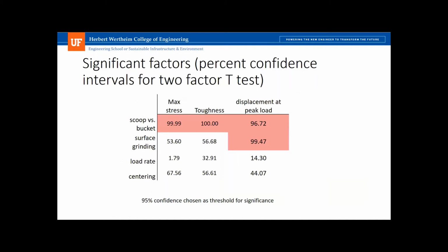But it didn't affect the stress or toughness. We found that the scoop versus bucket was very significant. How you make these samples really matters. If you're filling it with a scoop, you're doing scoop by scoop, you're basically filling the sample layer by layer.